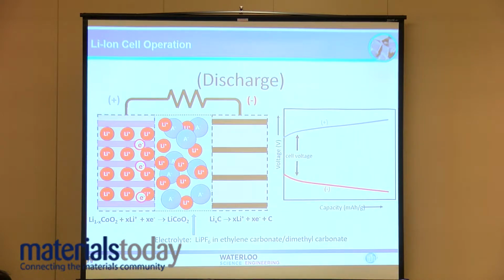And on charge, these cells can get up to fairly high potentials, up around 4 volts versus lithium, whereas at the negative electrode, we're fairly close to the reducing potential of lithium. And what's particularly important in these cells is not just the materials at the negative electrode, as we call it, and the positive electrode, but also the electrolyte, this little fuzzy blue stuff in the center. That contains a lithium salt and usually an organic solvent, which typically these days is an ethylene carbonate, dimethyl carbonate mixture, but a variety of carbonates can be used. And the interfaces are the real problem because that organic electrolyte is fundamentally reactive.